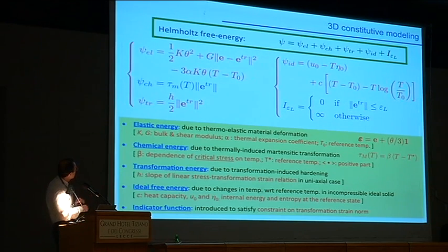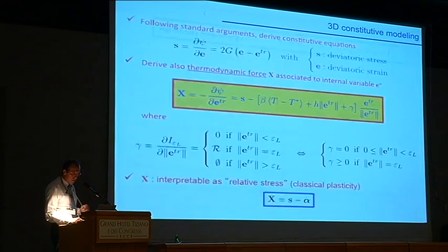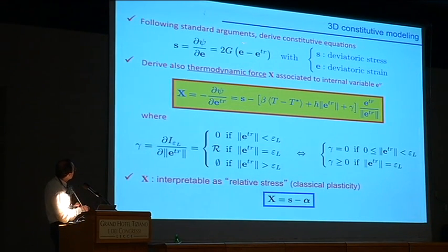Okay? So that's the free energy that's adopted. Then using standard argument, you can derive the stress, the deviatoric part of the stress. More interesting, you can derive the thermodynamic force associated with the internal variable. Here is the expression. Let me point out just that it's a function clearly of the internal variable, and in particular at the denominator here, you see the norm of the internal variable. And that's a source of problems because this quantity can be 0. So clearly we need to regularize this expression.